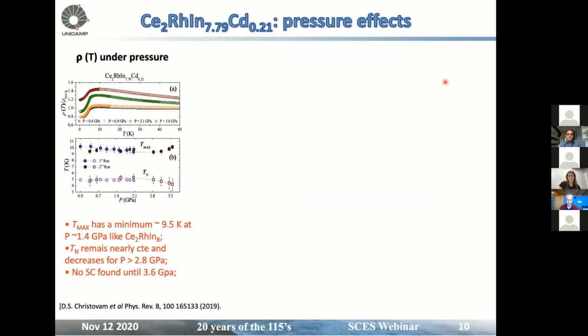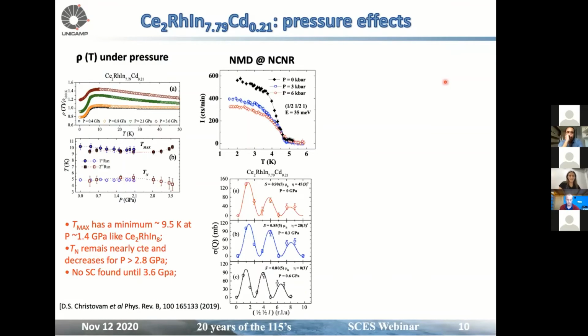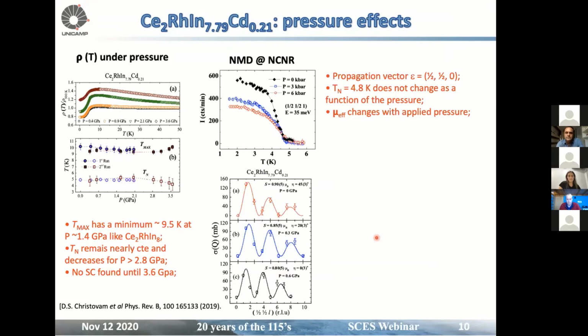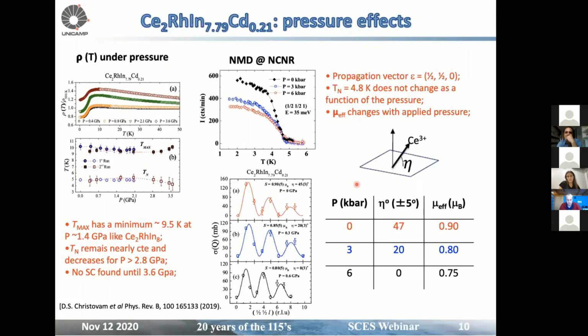gigapascal. So we performed neutron magnetic diffraction at NCNR. Those are intensity as a function of temperature and the model. So we see that as a function of pressure, the compound remains with the same propagation vector, the Néel temperature does not change, and the effective magnetic moment is decreasing. So that summarizes what we saw in the neutron magnetic diffraction experiment.